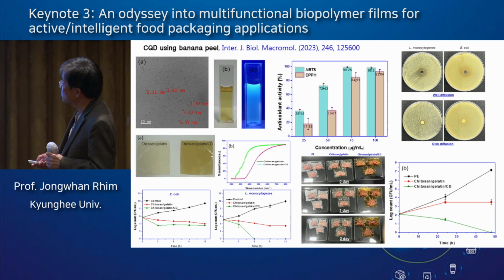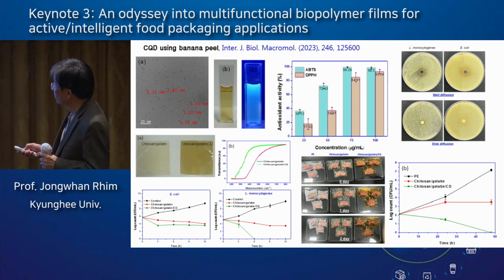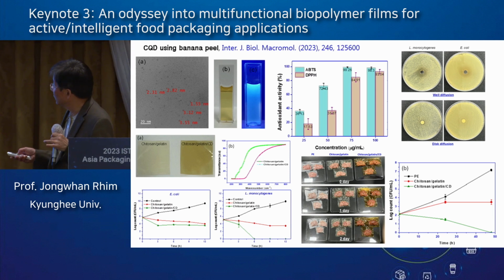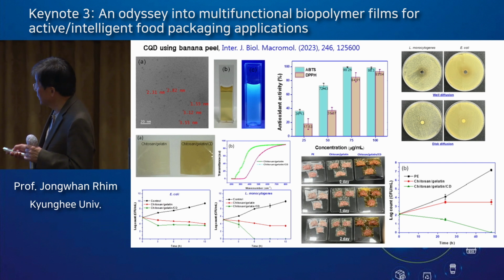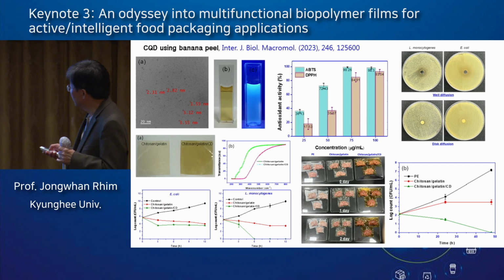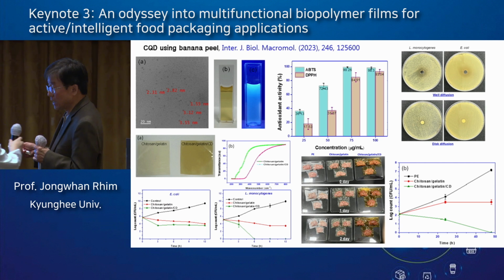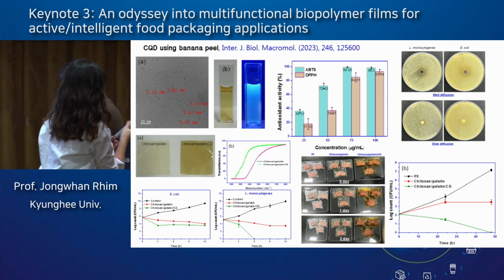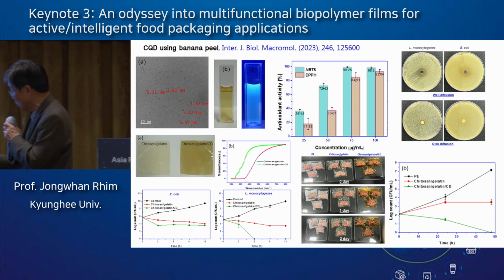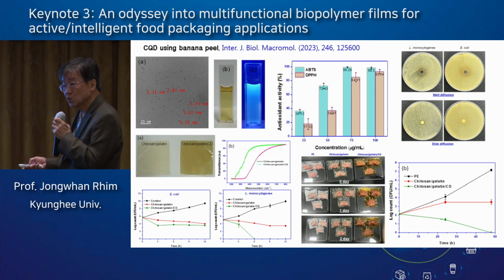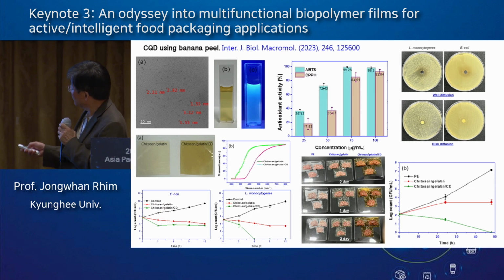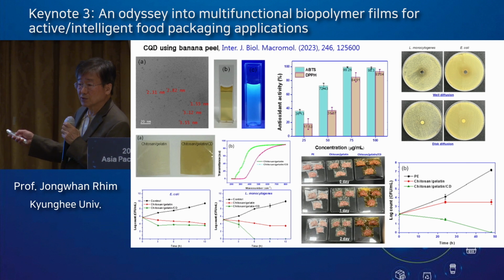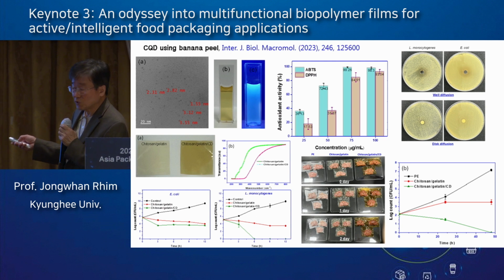We made carbon quantum dot using banana peel. It shows the antibacterial activity and antioxidant activity. This film, quantum dot added film, was used for packaging of meat. It shows the quantum dot added to the chitosan film to make composite films. This film was used to packaging this meat.